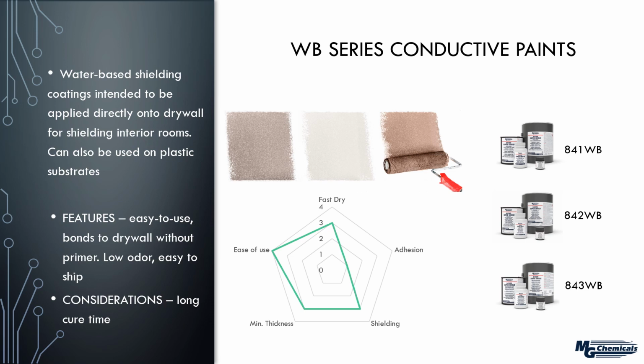So these are easy to use, they bond very well to drywall, there's no need for a primer, and because they're water-based, they're not only low odor, but they're easy to ship, and that's because they're not flammable. The consideration here is that they do take a long time to cure, and that's because with any water-based product, you need to let it first cure at room temperature before you apply any heat, and this is just to give the film enough time to properly form. If you rush it, you may in fact cause some cracking, and any kind of gaps in the film will result in poor shielding.